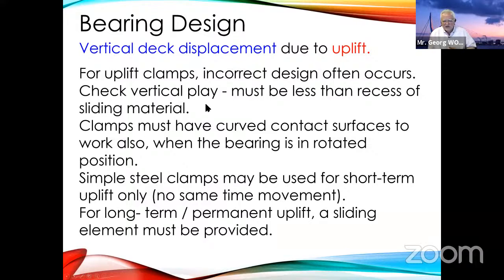The vertical play has to be very limited, smaller than the recess of the sliding material. Otherwise, the sliding material can be kind of sticking to the surface of the stainless sliding steel. And when you lift it up, then it goes out of the recess and it will not come back in the right position. And also the clamps must work in the rotated position of the bearing, so it must have a curved contact surface. And in a lot of cases, this was missing.